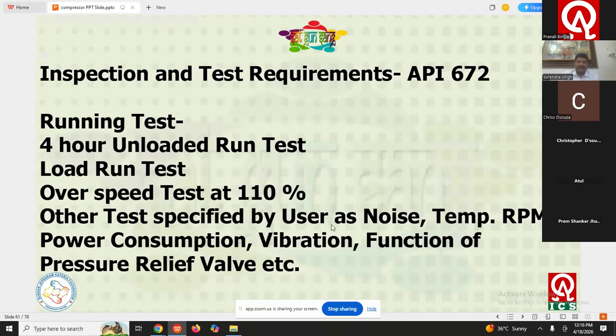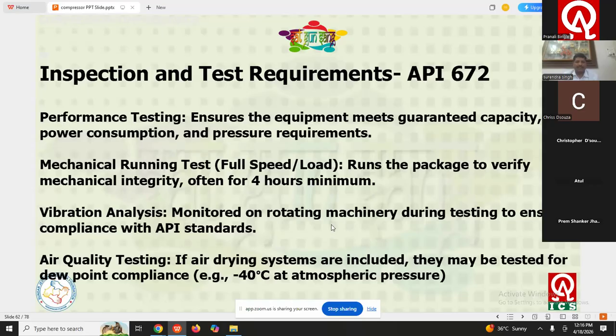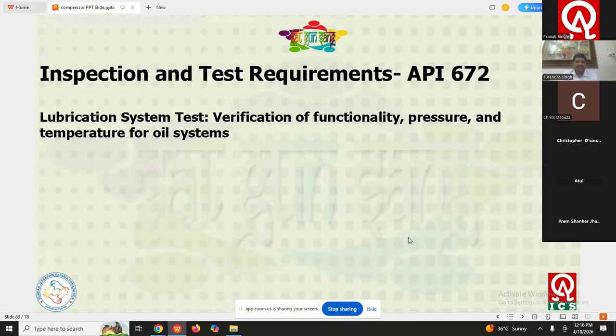Then the test specified by users has noise, temperature, RPM, power consumption, vibration, function of pressure relief valve, etc. These are few criteria that you have to check the full speed load, 4 hours, then the vibration analysis again, then air quality testing, a dew point also in this 672, a dew point check also you have to check. Lubrication system, visually you have to check the functionality of the lubrication system, then the pressure, then the temperature, and you have to measure also through the temperature indicator, through the pressure indicator that my lubrication system is doing during the operation is going in the right direction. Any abnormality is not observed, or the temperature is within the limit, pressure of the lube is within the limit.